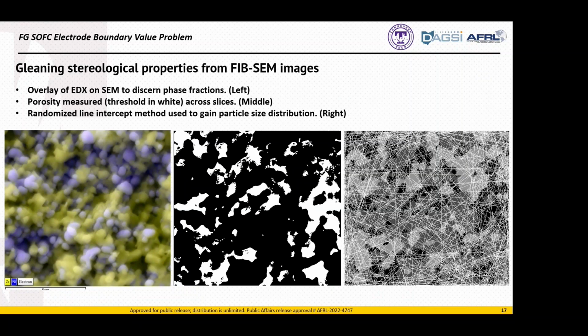One thing that we're trying to do is develop a model which uses parameters that can be gleaned just from two-dimensional images. The reason that we want to do this is because it's much easier, much cheaper to use two-dimensional SEM images than try to do full-blown 3D tomography reconstructions of these cells. So right now we're comparing our results to see if sampling across discrete cross sections like this and then adding up a few samples, we approach the same microstructure parameters that we would have arrived at had